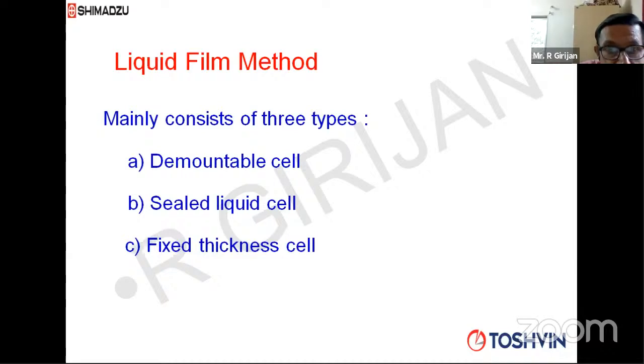Okay. Now there is something called a sealed liquid cell. A sealed liquid cell is normally used for semi-quantitative analysis. Sometimes people even use it for qualitative analysis, but it is mainly meant for semi-quantitative analysis, where you can change the path length by using different types of spacers. Spacer means thickness. You keep a spacer between 2 plates, and depending upon the thickness of the spacer, there is a path length difference between the crystals. So that's called a sealed liquid cell. And you can again open the cell, remove the crystals, and remove the spacer also, but that is only for semi-quantitative work.